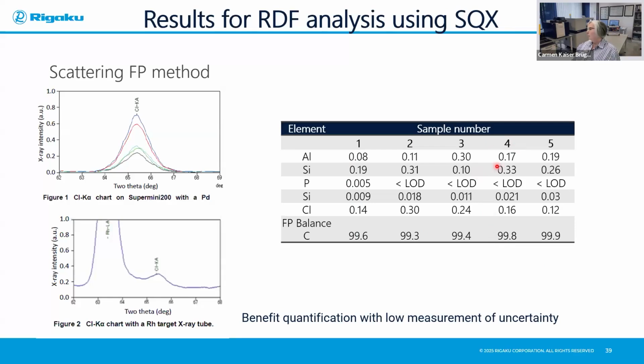So this result was done actually on our smaller instrument, which is the Super Mini 200 with a palladium source. The biggest advantage of the Super Mini in this case is the determination of chloride. Why? Because we have a very good peak to background ratio, because we have no spectral overlap from the rhodium tube, which we can conventionally get on our bigger floor standing instrument. So you can see here at the bottom, we also determined chlorine, but with a rhodium target. And of course, the drawback is we don't get a really nice peak to background ratio in this spectra that you see.